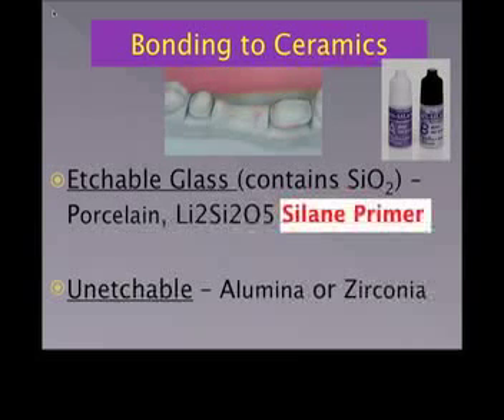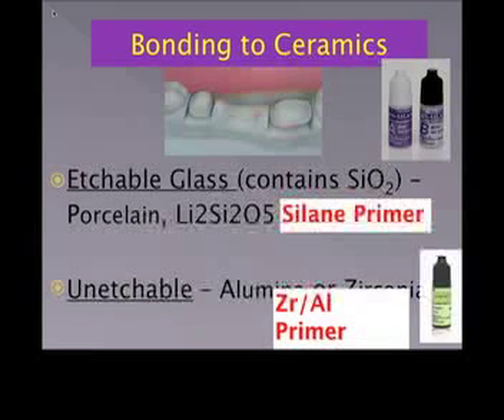The combination of primers containing both primers for metal oxide and silane primers is contraindicated. In other words, you don't want to use a silane on alumina or zirconia—it just won't do you any good.